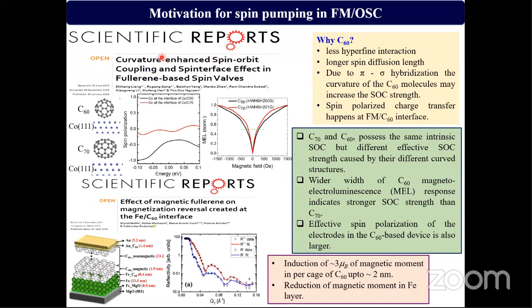Usually for spin pumping, high spin orbit coupling materials are used. But organic semiconductor materials are potential candidates because of their long spin diffusion length and less hyperfine interaction, and also these materials are low cost. But the problem is that their spin orbit coupling strength is less. However, it has been observed that due to the pi-sigma hybridization at the curvature of the C60 molecules, it may increase the strength of the spin orbit coupling.